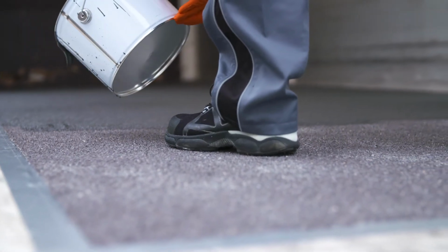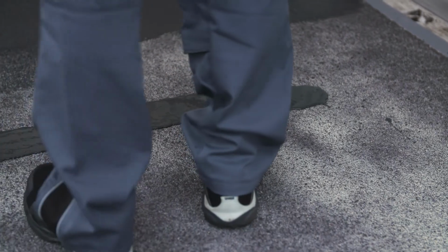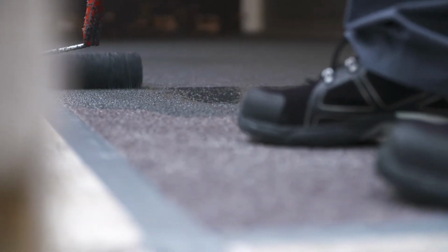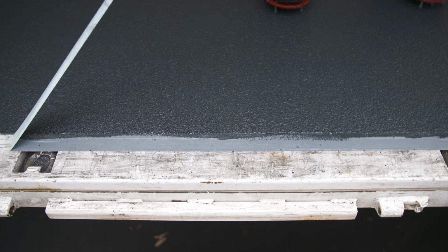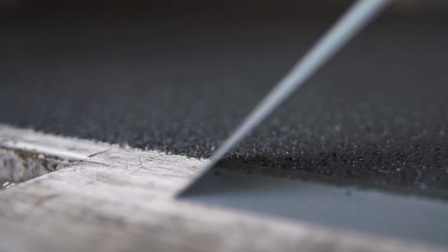Apply the liquid coating to the hardened and scattered surface with a nylon roller in a crosswise direction. And then remove the adhesive tape from the sides and screws. The surface, once sealed, must be left to harden for approximately 12 hours. After 24 hours, the coating is fully loadable and the loading area is ready for use again.